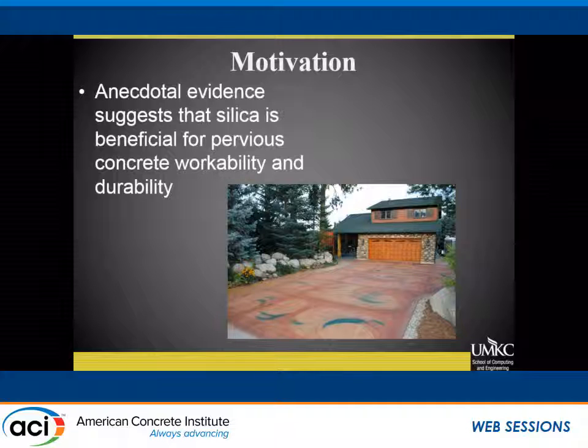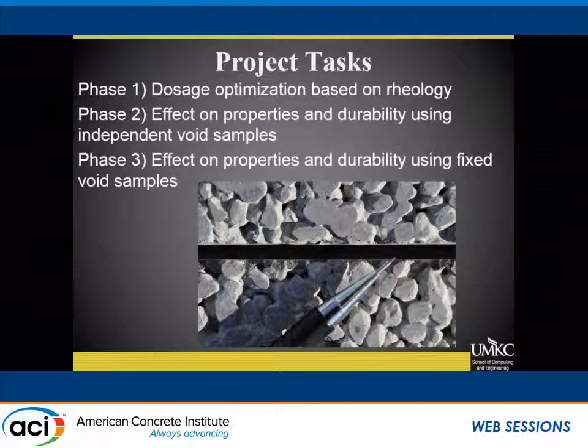So durability in the field, specifically for pervious, was related to what they saw for surface abrasion. So they thought the surface was a tougher material. And they took out cores and did the C131, the LA abrasion test, and said it was better than the alternative. So that's really what we're looking at for this study: does it impact workability, and does it impact durability? So this was really broken into 3 phases.